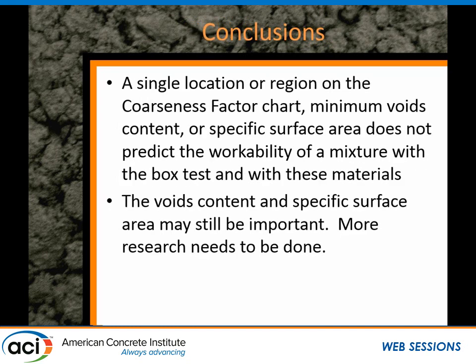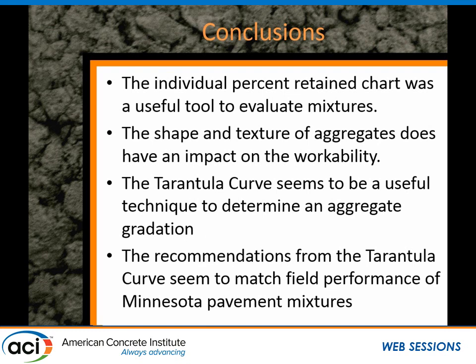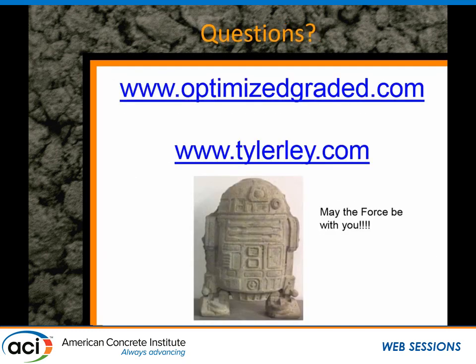In conclusion: a single location or region on the coarseness factor chart, minimum voids content, or specific surface area does not predict the workability of a mixture in the box test. The voids content and specific surface area may still be important — you want to be near the top but not necessarily at the top — but there are other things going on. The individual percent retained chart was a useful tool to evaluate mixtures. Shape and texture is important. The tarantula curve seems to be a useful technique, and its recommendations match the field performance of the Minnesota pavement mixtures. All of this is on optimizedgraded.com — specifications, papers, and Excel sheets are on there. Thank you.